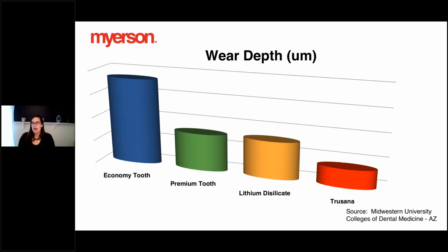I can't mention mechanical properties without at least mentioning wear depth. So what we did is looked at an economy tooth as a comparison and performed some testing. You can see that the wear is quite high comparatively. We also took a premium tooth, looked at the wear testing, and while it's much lower and on par with lithium disilicate, if you compare Trusana with these other three materials, the wear for the same amount of time is actually about half or much lower. And again, these results are performed by a third party out of house as a comparison.